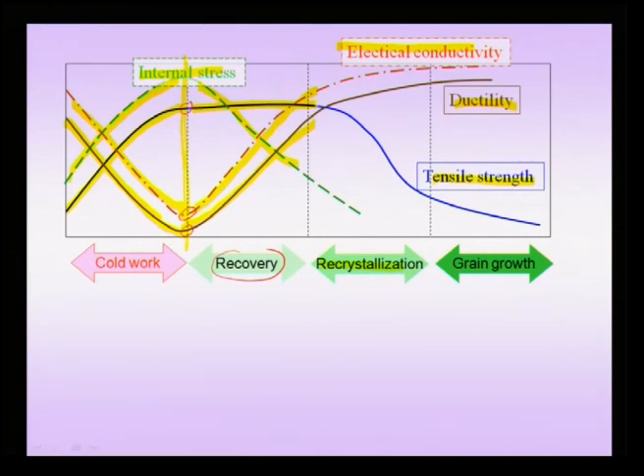If I further hold the material at a higher temperature to cause recrystallization, during recrystallization of course what happens is that my tensile strength also comes down. Since I already have my electrical conductivity at a sufficiently high value, it will tend to recover a little more because my dislocation density is coming down, but there is no pronounced change during the recrystallization process. But the important change takes place to tensile strength, which seriously falls down, and therefore if I cause recrystallization of the material, my material from strong becomes weak.